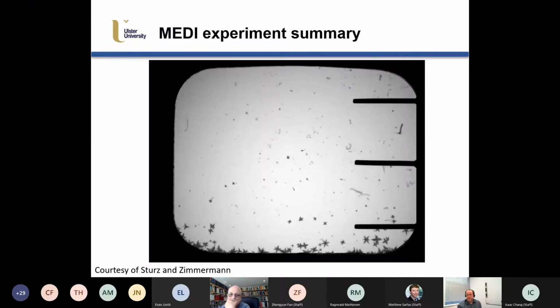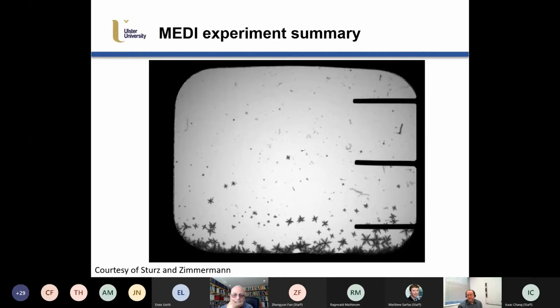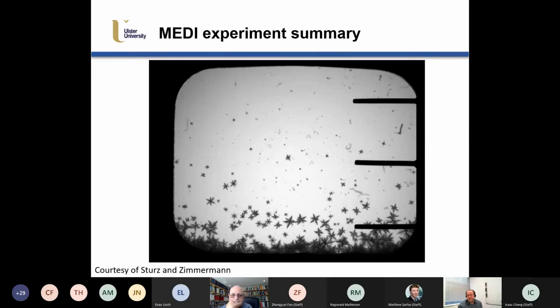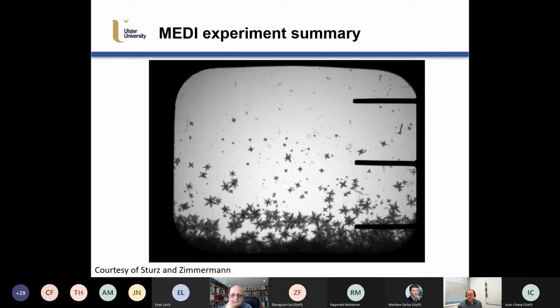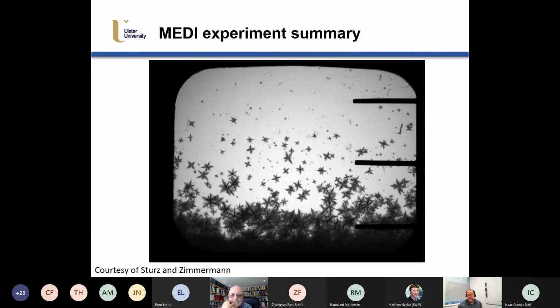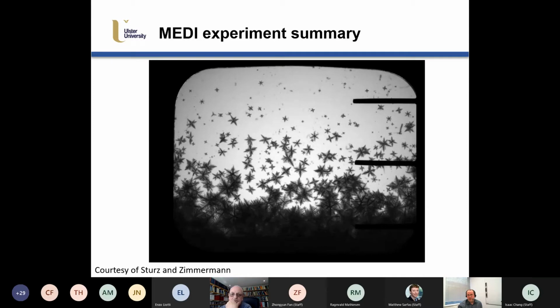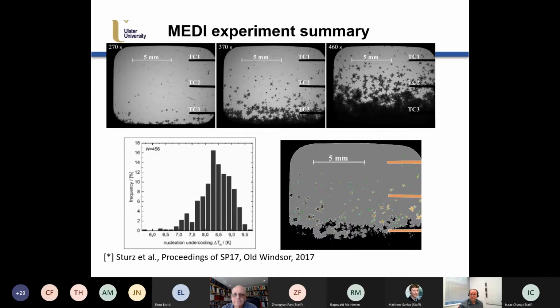And hopefully you can see a video of the microgravity video data that was obtained. You see there's a slight temperature gradient, so it's slightly cooler at the bottom and slightly hotter at the top. Then you see the solidification coming up. That was as much as they were able to do in microgravity, but it's a lot, and there's some good information there. They were able to get the frequency of the nucleation events. They were also able to do some thresholding of the images to get the area fraction. So all of this data was out there.